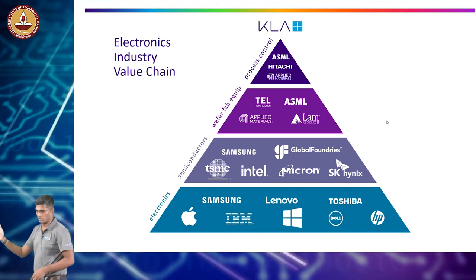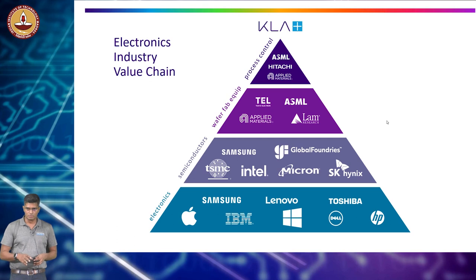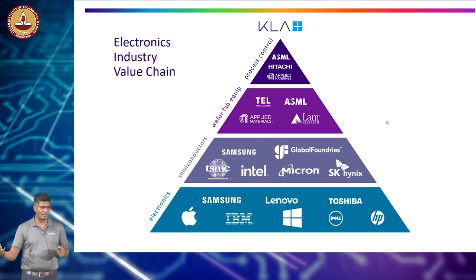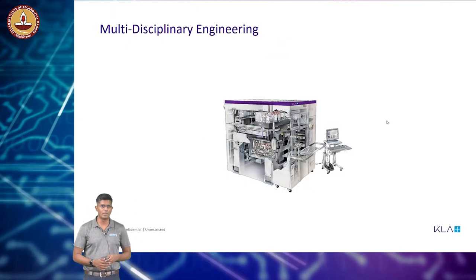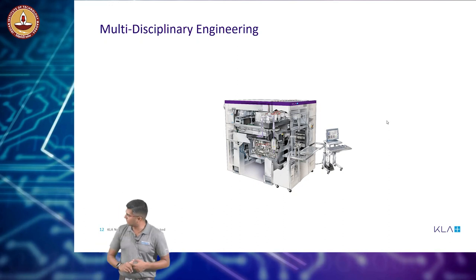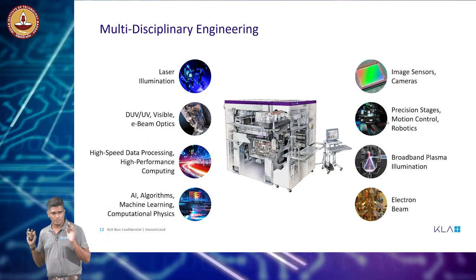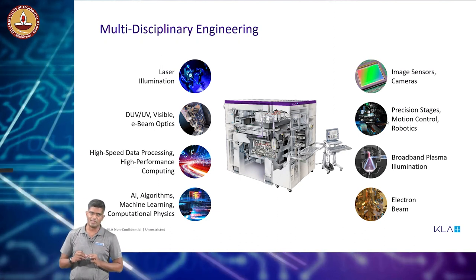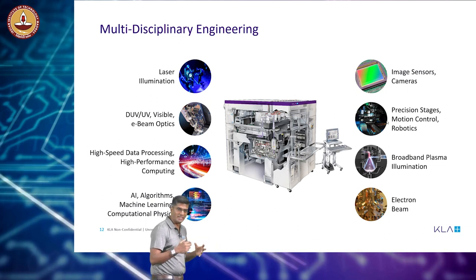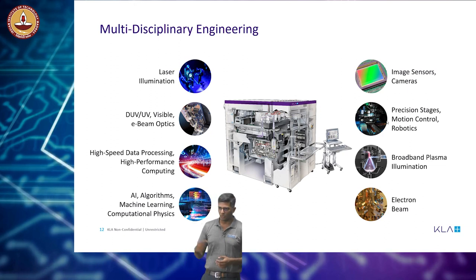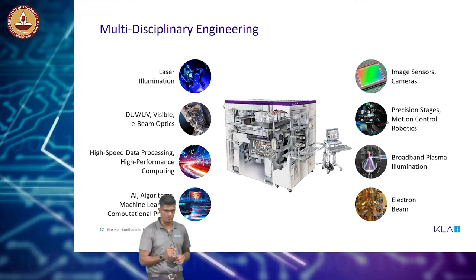There are some steps in the manufacturing process — which typically happens in factories that are kilometers long — for which only KLA produces tools. These tools are fundamentally image processing tools because you do not have an electrically testable circuit: you take an image, process it, and check it against a reference. The tool itself is a multi-disciplinary engineering feat. The factory in which semiconductors are manufactured is about 10,000 times cleaner than an operating theater. A single speck of defect can really ruin your entire wafer. Our tools sit inside those fabs to make sure you find those defects.